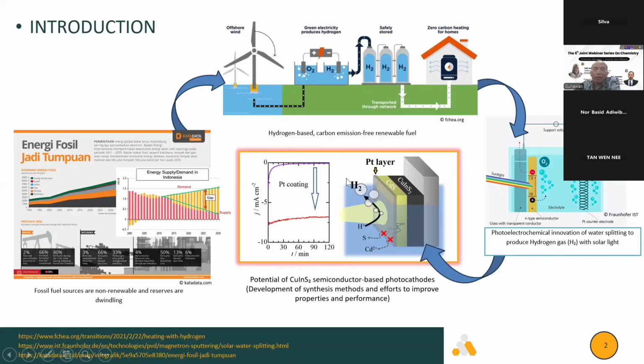And there is the potential of a copper indium sulfide semiconductor-based photocathode, with the development of synthesis methods and efforts to improve the properties and performance. The absorber is copper indium sulfide on molybdenum-covered glass. Then it is covered with cadmium sulfide, and we use a co-catalyst to improve the performance. In this case, we add platinum.